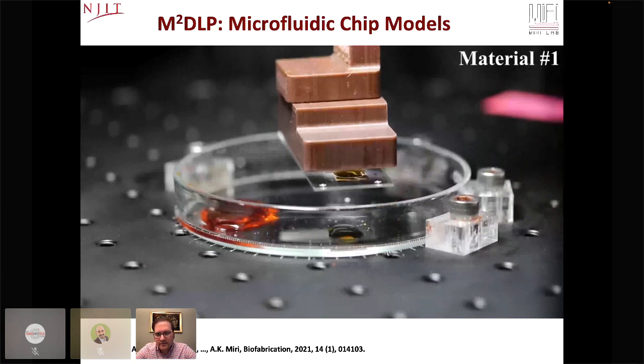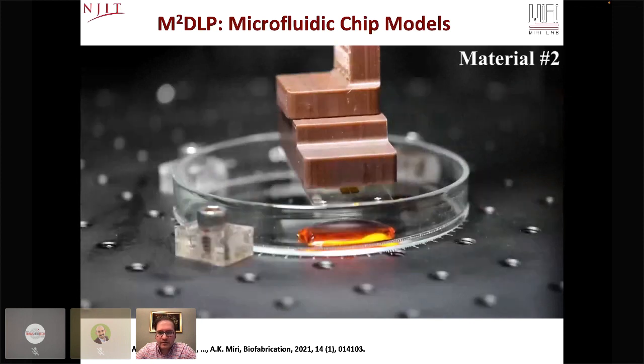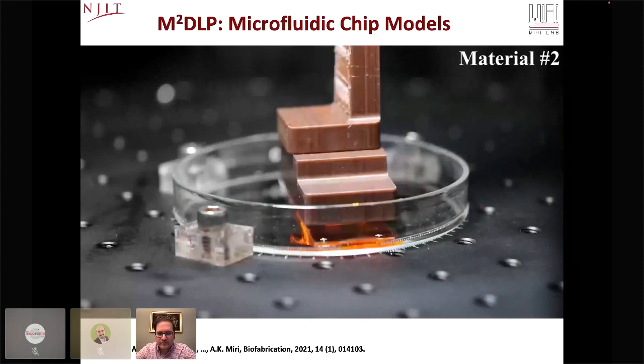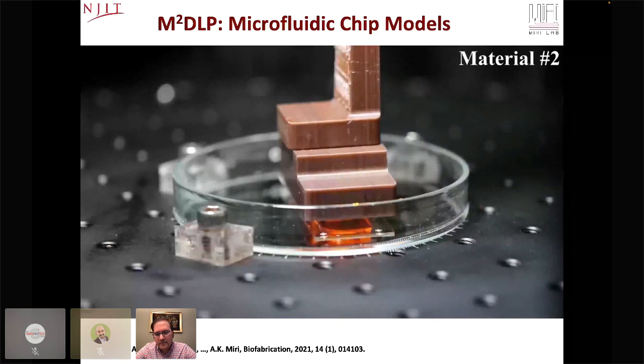And you can see after it's washed, there's a residual, and it goes to the second material, which is polyethylene glycol, the PEGDA, and it's for stability of the structure. So you have a cell-laden part enclosed with the PEGDA as the structure of the microfluidic chip, and you can see this is again real-time fabrication, so you can see the timing is pretty quick, and per each layer, we only needed less than a second of patterning.